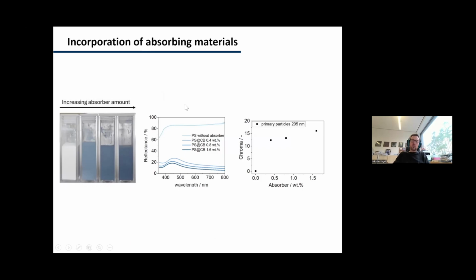And if we look at the reflectance spectra of such materials, we see exactly what I discussed before. If we have too much scattering, then we don't see any color, so the entire spectrum reflects and it creates a whitish appearance. And as we add carbon black, we see that we suppress the scattering more and more, and as a result, the photonic stop band starts to dominate the spectral properties more and more.